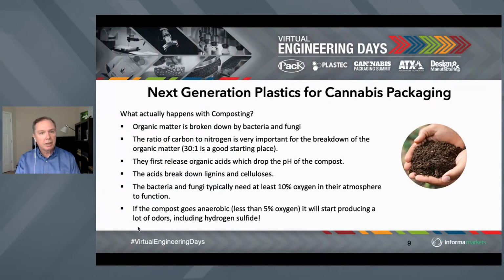So what actually happens with composting? Organic matter is broken down by bacteria and fungi. The ratio of the carbon and nitrogen within the material is really important for the breakdown of the organic matter. You see, I have listed there the 30 to 1 is a good starting place for it. What happens when composting takes place is that the first thing that happens is there's a release of organic acids which drop the pH of the compost. These acids start in and break down lignins and celluloses, particularly with paper products and things along those lines. The bacteria and fungi typically need 10% oxygen in their atmosphere to function. So they will function without oxygen, but it promotes a different type of breakdown.